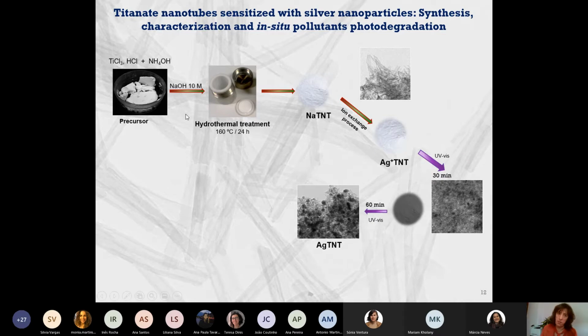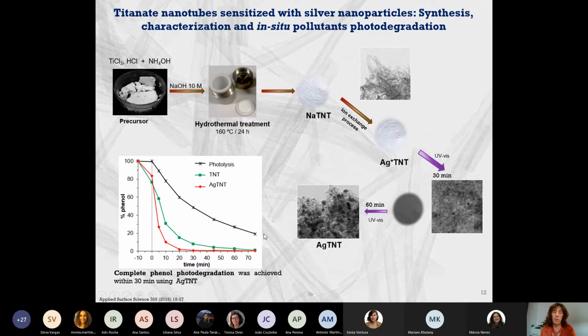So we have prepared the precursor, hydrothermal treatment, and we have prepared titanate nanotubes. Then we decide to use this material to remove Ag+ from water. And of course, we have an ion exchange process, and we will have titanate nanotubes with Ag+. Then we decide to use this material under UV radiation, and we start to see the formation of some silver particles. And if we increase the time of radiation, we will have the formation of more nanoparticles. And when we use this material for the photocatalytic degradation of phenol, we can see that, in fact, this material is a better catalyst than the first one.